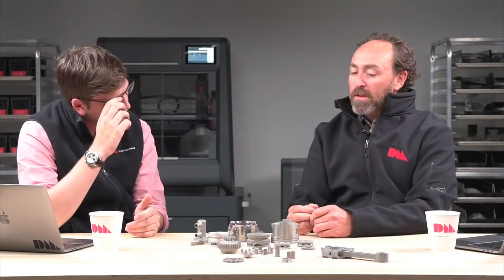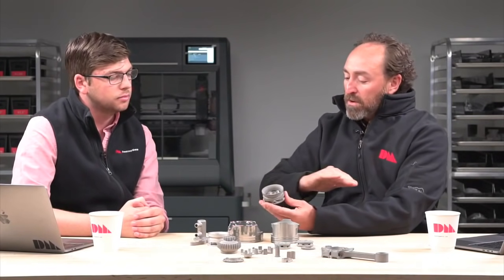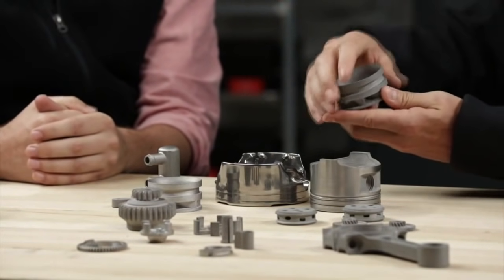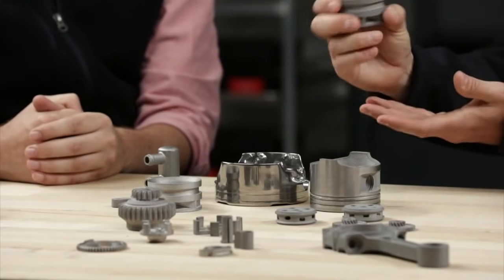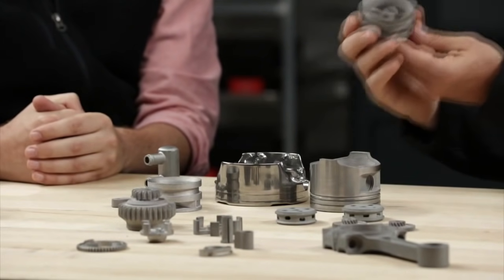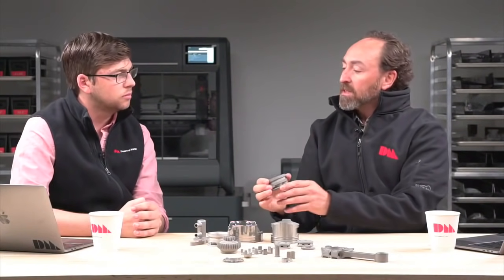Awesome. So how does part shrinkage affect the final dimensional accuracy of parts? Yeah, so most of our tolerances come in due to the shrinkage of the part. Printing is very accurate. So for instance, take the production system, for example. We print at 1200 dots per inch, or DPI. Very high resolution images create the green parts in the powder bed. But when those very high accurate parts are put into the sintering furnace, the part shrinks, and it shrinks by up to 17%. That's all taken care of in the software, but there is tolerance with shrinkage, and the tolerance is very similar to that of a casted part.